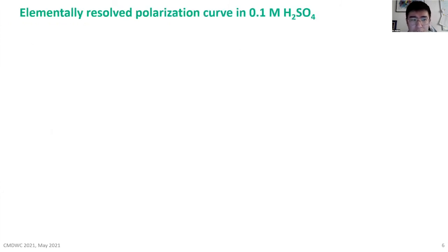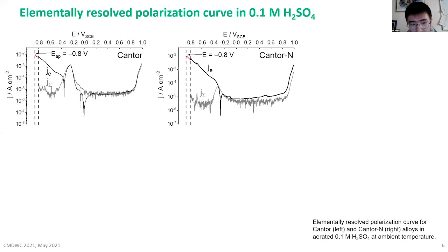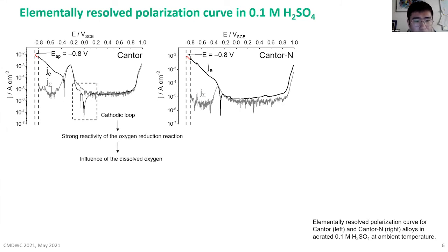Further insights into this phenomenon could be obtained by the elementally resolved polarization curve in 0.1 molar sulfuric acid. Dr. Han has introduced similar results to you. So this curve shows the conventional polarization curve via the black lines, overlaid with the sum of the elemental current detected by the ASEC technique. And we applied a cathodic potential at the beginning to remove the passive film. On the left figure, we observe this cathodic loop, and we attribute this to a strong reactivity of the oxygen reduction reaction occurring at this potential domain. So it raised a question: what is the influence of this reaction on the spontaneous corrosion behavior? It has been investigated and will be shown in the next slide.